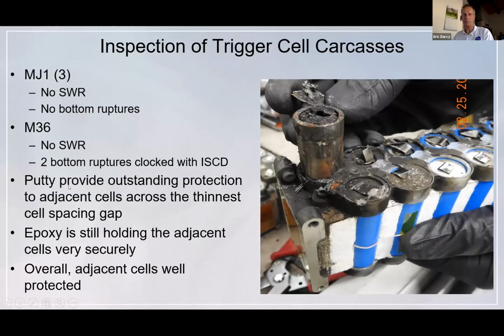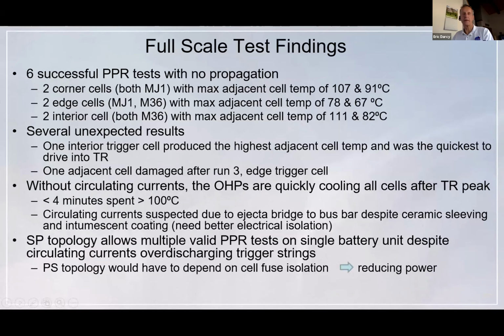So we thought the putty did a really good job of protecting and providing support to the can wall of these cells, especially these high energy cells. The can walls are getting thinner and thinner, and so they need to be protected. So overall, the adjacent cells were well protected. We did 6 of them: 2 corner cells, 2 edge cells, 2 interior cells. Maximum temperatures were just above 100 degrees on some, but we were able to cycle the adjacent cells, or cycle the battery, afterwards. So it showed that we had good margins against that.